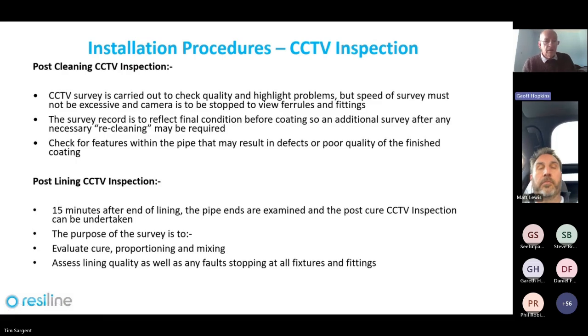We also, going slightly out of sequence here, after we've lined the pipe with our material, 15 minutes after the end of the lining, you can examine the pipe ends and CCTV inspect the lining. And the purpose of the post lining inspection is to evaluate the cure, proportioning and mixing of the lining, check nothing's gone wrong during its application, and you can assess the full lining quality. And both of these surveys are recorded and are kept as part of the mandatory lining records that we have.